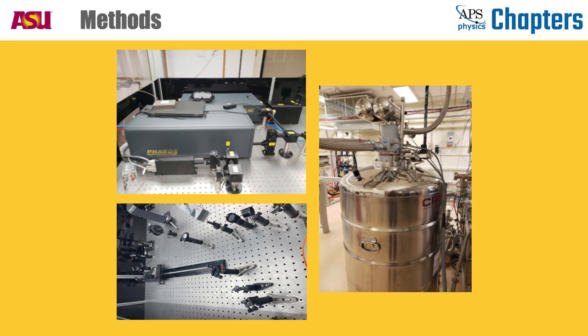In order to perform the MTE measurements, we used our ultra-fast laser connected to an optical parametric amplifier. This allowed us to measure the MTE and quantum efficiency for a variety of photon energies. We also have a liquid helium plant connected to a helium recirculation line which allows us to make continuous measurements at cryogenic temperatures without ever running out of liquid helium. All of this was necessary to see if we can measure the lowest possible MTEs that can be achieved with non-graphene coated single crystal copper photocathodes.